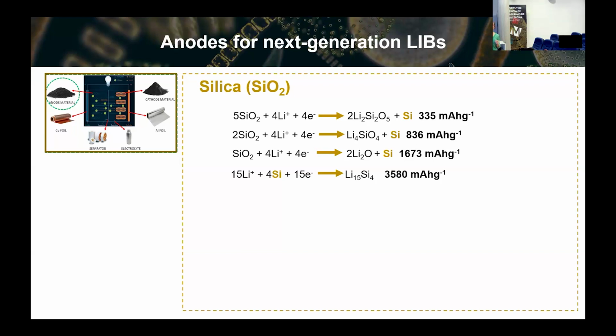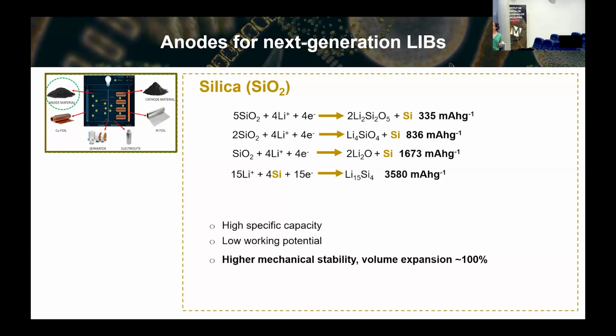And these phases are supposed to be electrochemically inactive, meaning that the general understanding that we have of this system is that silicon will be formed in a matrix of inactive species. So these inactive species can act as a mechanical barrier for the expansion of silicon, because then it doesn't have that much space to expand. And we think this is the reason behind the higher mechanical stability of silica anodes if we compare them with silicon. Of course, this comes at the cost of a lower capacity, but still much higher than graphite. And still, the volume expansion is considerably high. It's not as high as silicon.